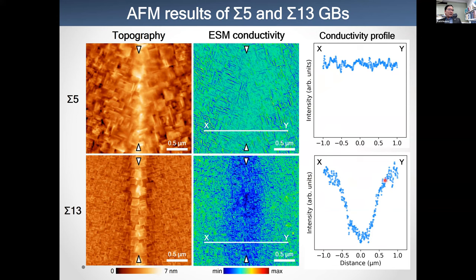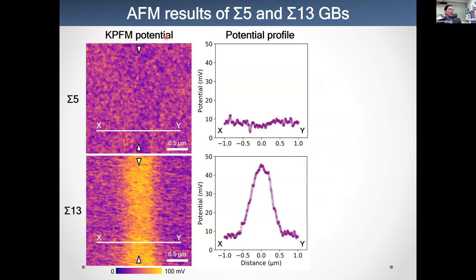In this way, there is a much decrease like that. So lithium ion is hard to diffuse along certain grain boundaries. This is a KPFM potential. At sigma 5, there's no charge along the XY direction, but the sigma 13 boundary is positively charged, like that.